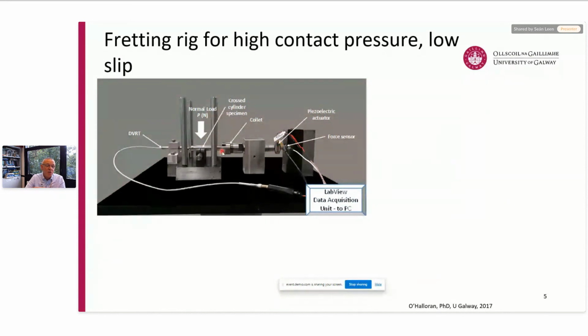It's a cross-cylinder arrangement where basically we've got two cross cylinders with another one which moves in and out. And there's a normal load applied by a dead load. And you can see three cross cylinders in total, two of them, one above and one below a test specimen, which is then cycled tangentially between those. And then there are various sensors, etc., there to measure displacement and to measure force, and that's implemented in a closed loop control system via